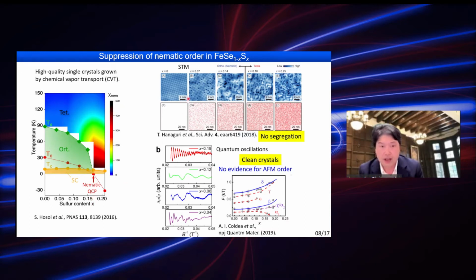By looking at STM, you can find the position of sulfur atoms, which shows no segregation, meaning we have pretty uniform superconducting single crystals. If you apply a high magnetic field, we can observe quantum oscillations, indicating these crystals are pretty clean. So we have very uniform and very clean single crystals in a wide range of x. This is a very important step to understand the physics of this material.